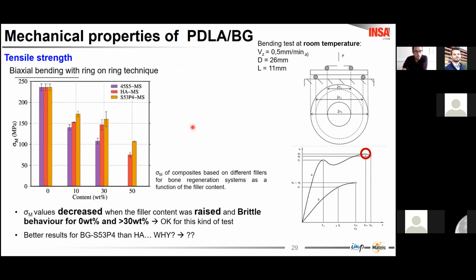As previously observed by compression or tension, the strength decreased when the filler content was raised. Almost all the samples presented brittle behavior, but in the case of S53P4, for example, they present better mechanical properties than hydroxyapatite.